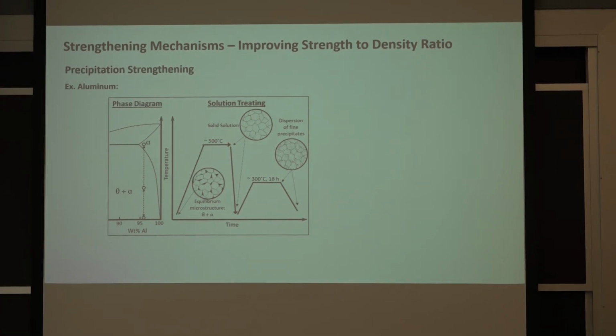That slab will have what's called an alpha plus theta microstructure, so it's a dual phase material that comes straight from the mill, straight from being solidified after being mixed together. What they'll do for like a 6000 series aluminum or a 7000 series aluminum, which are common aerospace alloys, is heat that material up to about 500 degrees Celsius until it forms a solid solution.